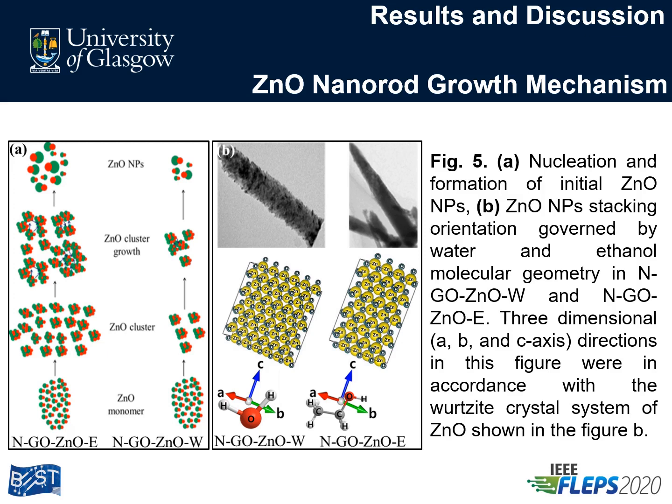Water has more atoms to propagate interactions in M-plane than ethanol. Therefore, zinc oxide nanorods with a low aspect ratio were obtained in nanomaterial prepared in water solvent. This detailed spectroscopic analysis shows that the zinc oxide nanorod obtained in the presence of ethanol showed a higher aspect ratio, while it was lower in the presence of water.